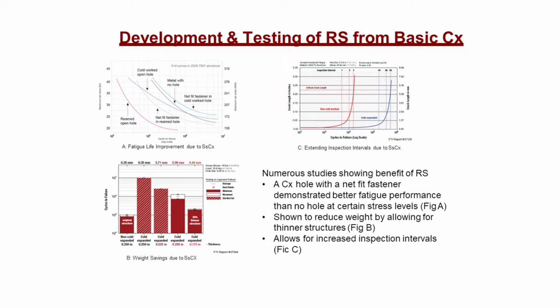The bottom line is a hole treated with nothing. It's just an open hole. And then you have that blue line is a hole cold worked. The next two lines are the one second from the top is a metal with no hole. And then that top one is a hole that's been treated and then has a net fit fastener. So when you put that net fit fastener inside that hole, it makes it even stronger than if there was no hole at all. When you install an interference fit fastener into that hole, the protection gets even greater.